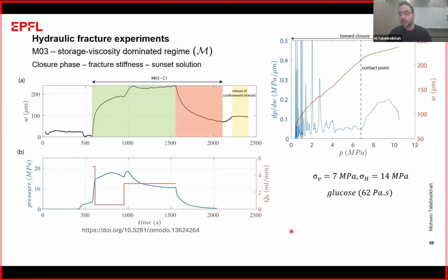Yeah, this is completely true. I do agree with you that we have some contradiction with the sunset solution assumption, but I saw a paper from Anthony Pierce showing that they could see this sunset solution when there is a proppant, and we can assume that this proppant can have the role of this residual opening. But I do agree with you. We have some contradiction with the sunset solution because the sunset solution says that we do not have any opening after the closure and it just closes completely. But what we can see from the experiment is that there is a residual opening at the end of the experiment.